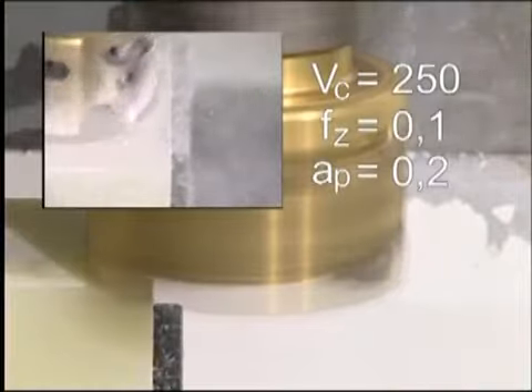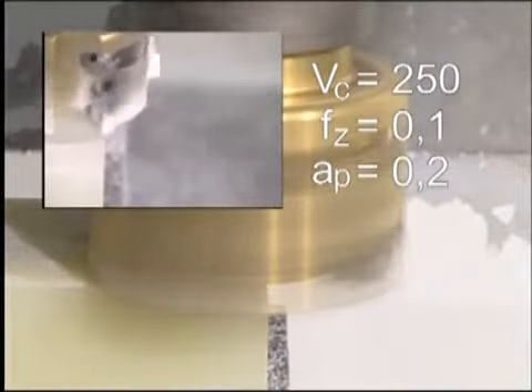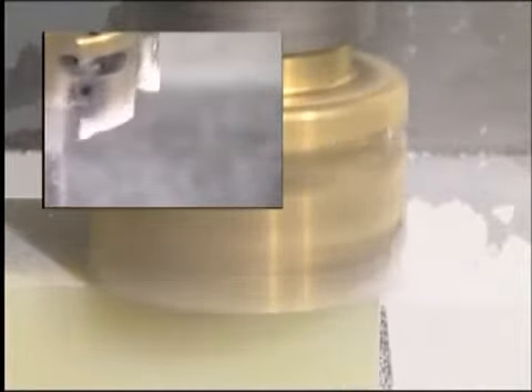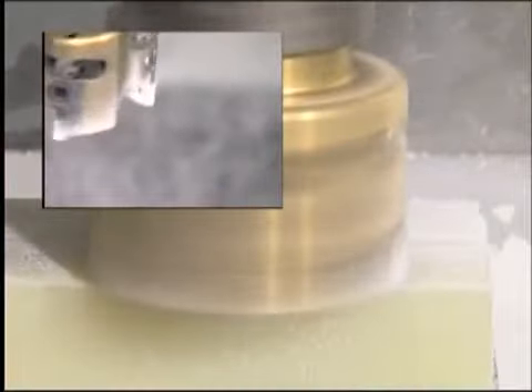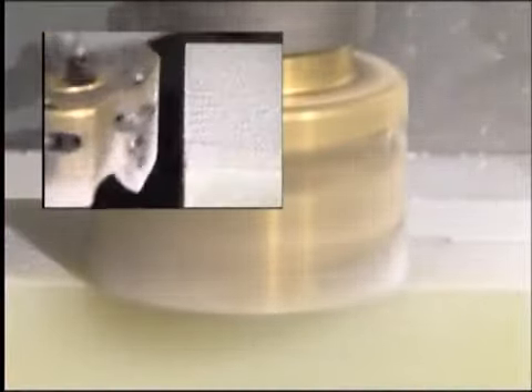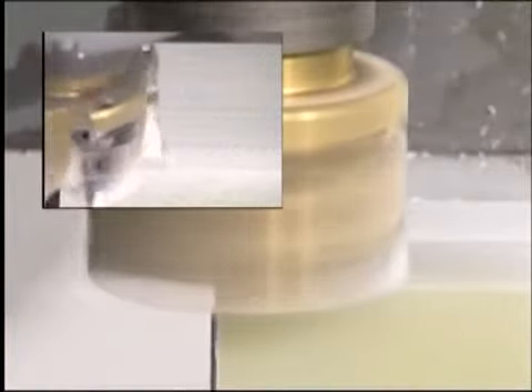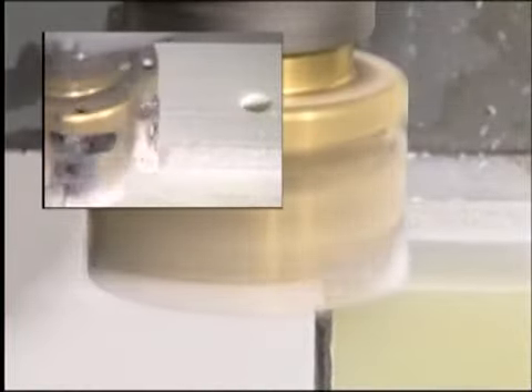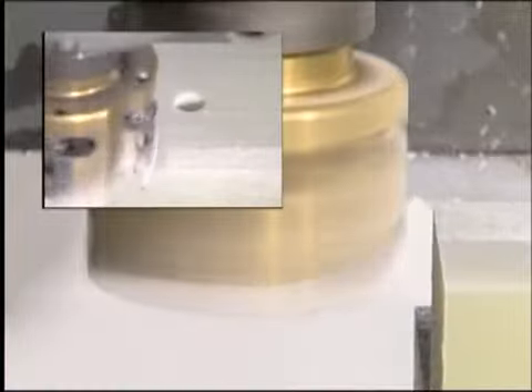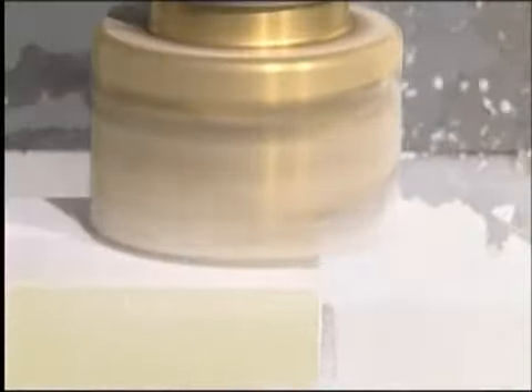Next we demonstrate the machining of Vetronit ESG 619, which is in fact a pressed layered material on the base of epoxy resin and glass fibers. Due to its high percentage of glass, approximately 80%, this material has been considered to be virtually unmachinable.